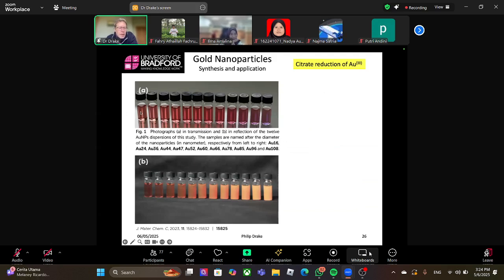So, particles: small, a nice deep red color; big, more a violet color. This is in transmission mode, when the light is coming through the sample towards your eyes. As you get these larger particles, you start to get scattering. Small particles, 20 nanometers in size, have a red color and no scattering. As the particles get bigger, the light can hit the particles and get bounced off towards you. So now we're seeing scattering. The solution is no longer transparent. It has scattered light as well as transmitted light.